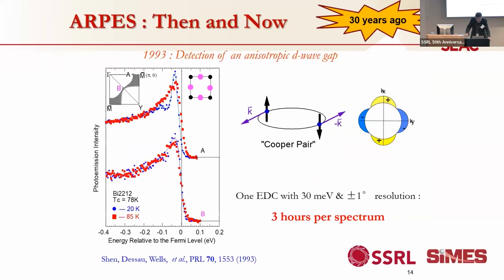That was the earlier paper, okay, of the D-wave gap structure. We did the experiment at SSRL with the samples from Aharon Kapitulnik's group and with a lot of insights from Doug Scalapino. And you can see that at the time, we could only take 3 spectra because your surface needs to be clean. Okay, so we have about 10 hours before the surface has other things condensed. So that factor of 10 improvement of the detector made a critical difference because you wouldn't have the signal to noise.